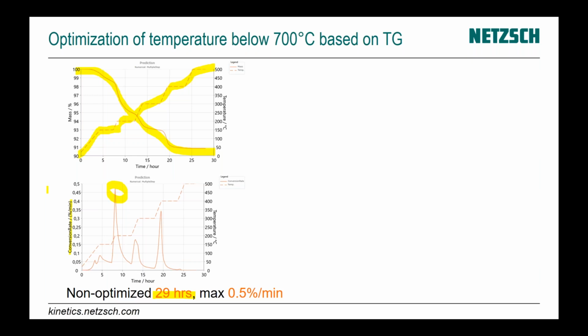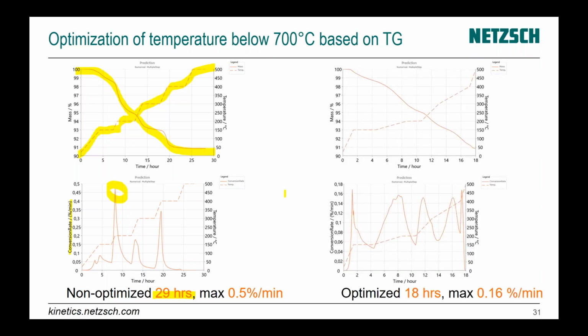And now we can make optimization. We can reduce this spike, and we can make it as short as possible. After optimization, we have a new temperature profile, and we have a new mass loss or debinding range. The real optimized profile is much shorter, and the height of the spikes is less than the original. So we have improved quality, and we have reduced the firing time.